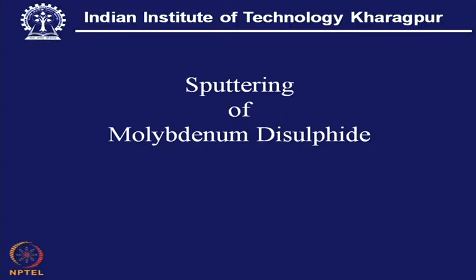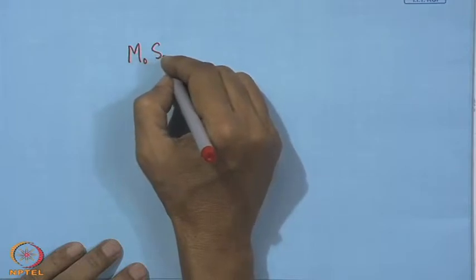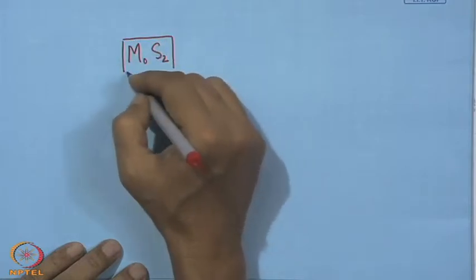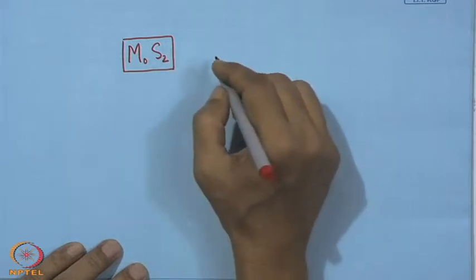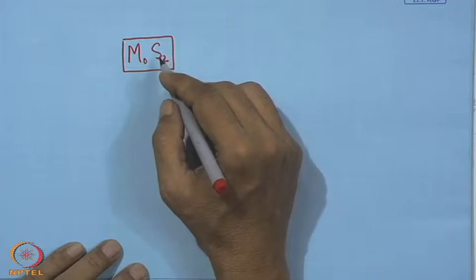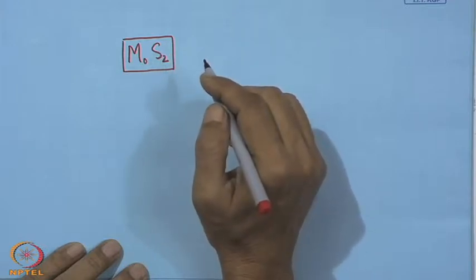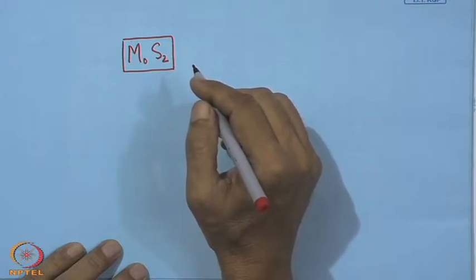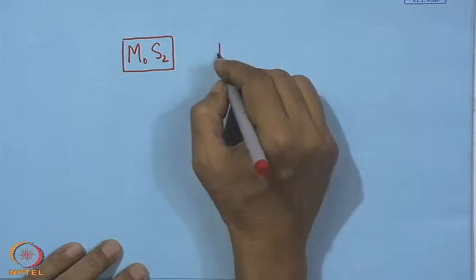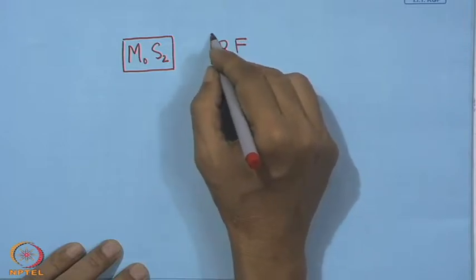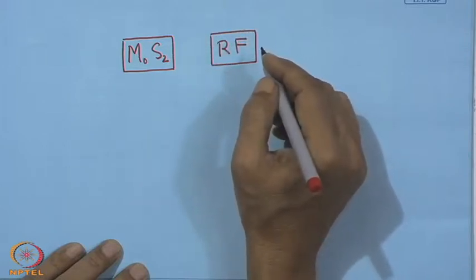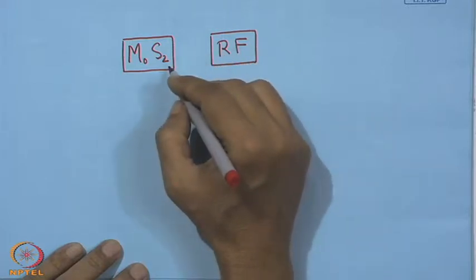Now, what we can see further is the sputtering of molybdenum disulfide. This MoS2 sputtering is possible by at least two processes, because it is not a very good conductor of electricity. That is why earlier DC sputtering was not very popular, and mostly it was RF, radio frequency sputtering, and we know that with RF it is possible to use a non-conductor or a poor conductor as one of the target materials.